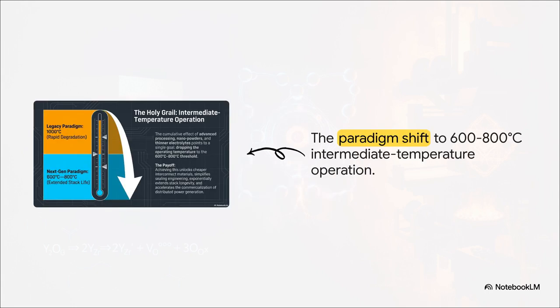And all of these advanced processing techniques point to a single, triumphant payoff: dropping the operating temperature. By shifting from the legacy paradigm of 1,000 degrees down to the 600 to 800 degree threshold, we unlock cheaper interconnect materials. We finally solve the nightmare of seal degradation, and we exponentially extend the lifespan of the entire power stack. It accelerates the entire commercialization of distributed power generation.